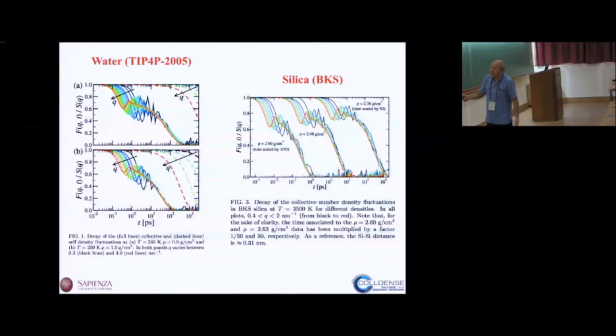And you have seen this at different state points. We've seen this also in silica. We have simulated different densities, different temperatures. You see that the alpha relaxation time for all wave vectors, again, those are quite large systems, behaves in the same way.